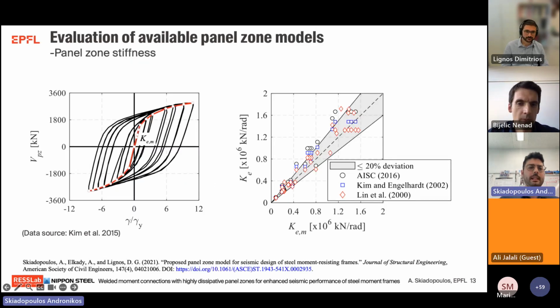From the collection of the test data described before, the experimental panel zone elastic stiffness is deduced from the first cycle envelope, as shown on the left side of the slide, where we have a typical response of a panel zone. In the vertical axis we see the panel zone shear, and in the horizontal axis the normalized panel zone shear distortion. So from the first cycle envelope of the hysteretic panel zone response, we extract the panel zone elastic stiffness, and we call it KEM, which is shown in the horizontal axis of the right side figure.